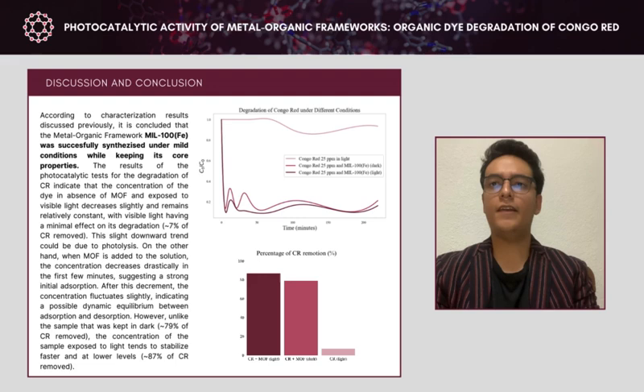The results of the photocatalytic test for the degradation of Congo Red indicate that the concentration of the dye in absence of MOF and exposed to visible light decreases slightly and remains relatively constant, with visible light having a minimal effect on its degradation. Approximately 7% of Congo Red was removed in this case. This slight downward trend could be due to photolysis. On the other hand, when MOF is added to the solution, the concentration decreases drastically in the first few minutes, suggesting a strong initial adsorption. After this decrease, the concentration fluctuates slightly, indicating a possible dynamic equilibrium between adsorption and desorption.